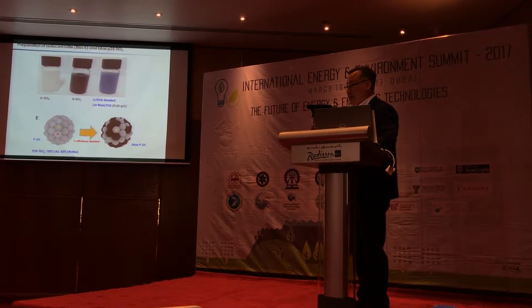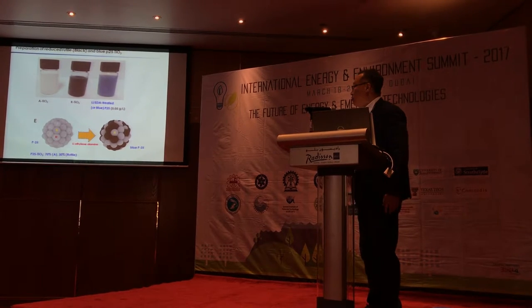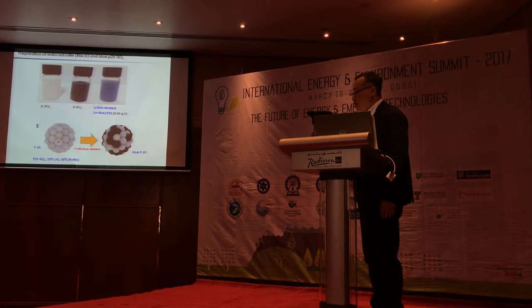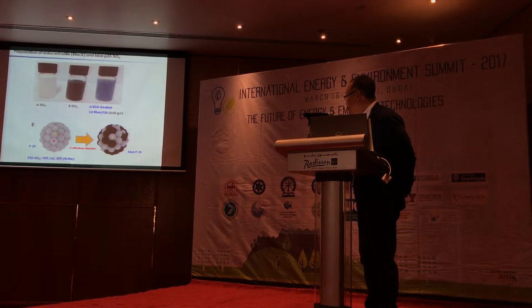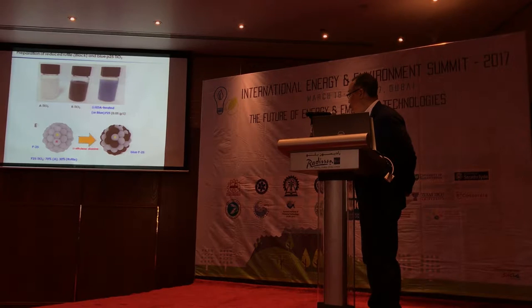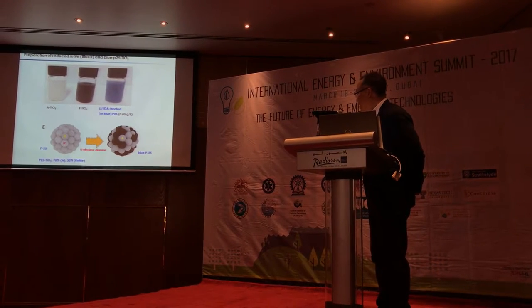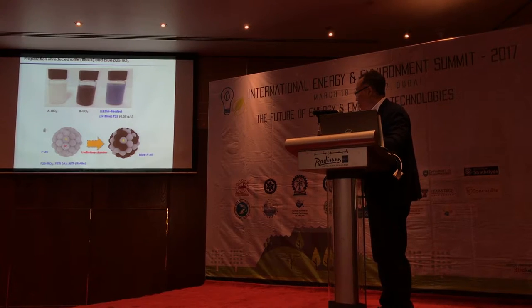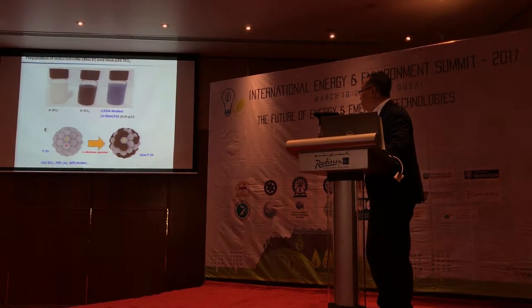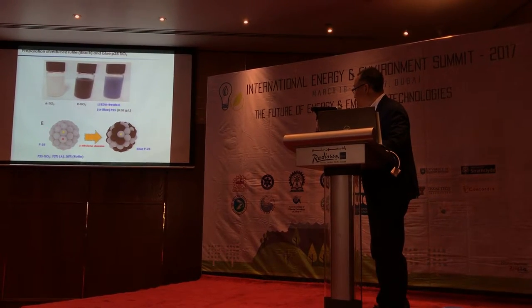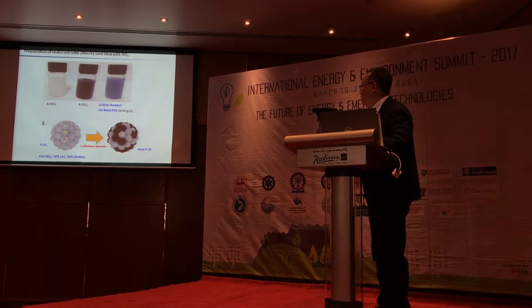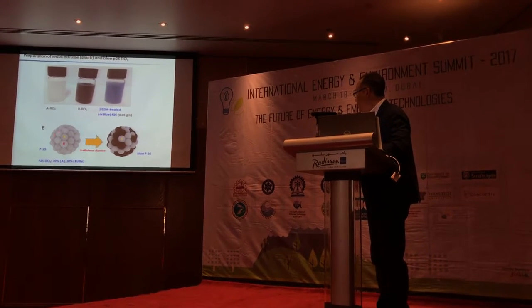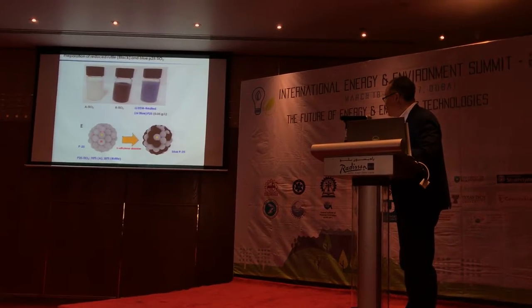Fortunately, we found out a new reagent which can do a solution process, also at room temperature without any hydrogen gas. By using this new reagent, which is lithium ethylenediamine — known for a Birch reduction reaction, which can give an electron-rich solution — through this reaction, we use P25, which consists of 70% anatase phase and 30% rutile phase.